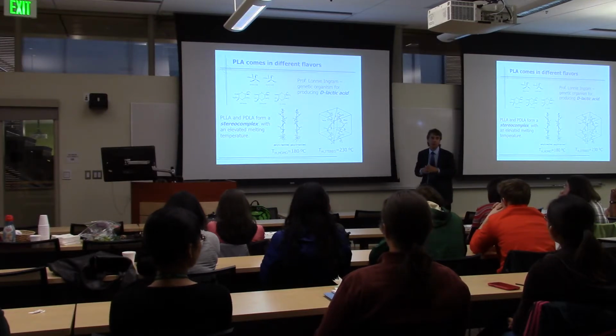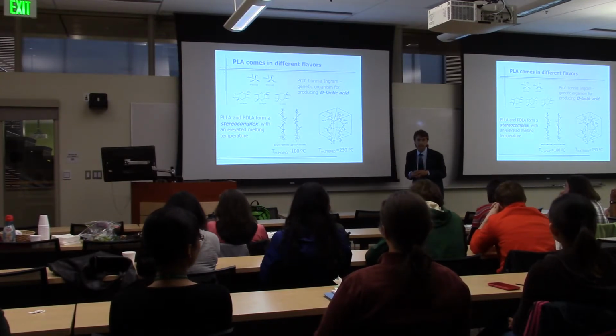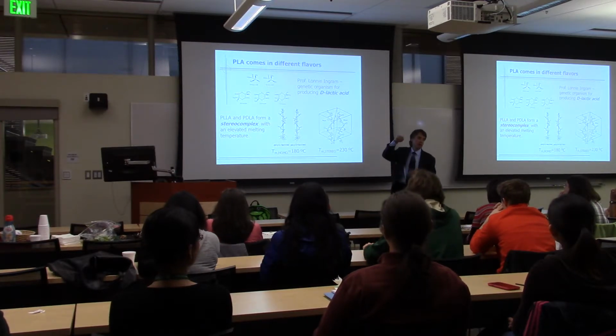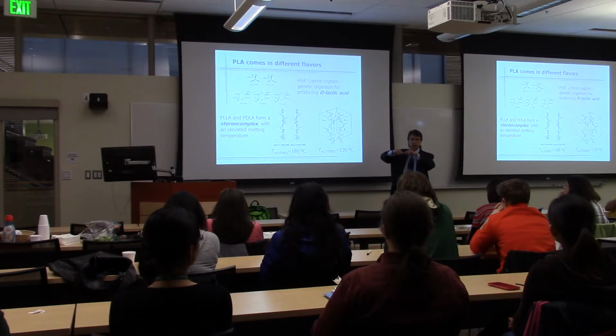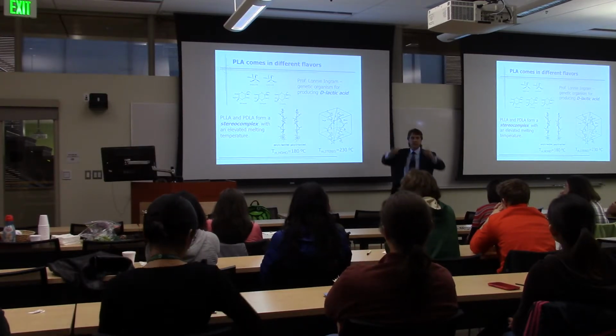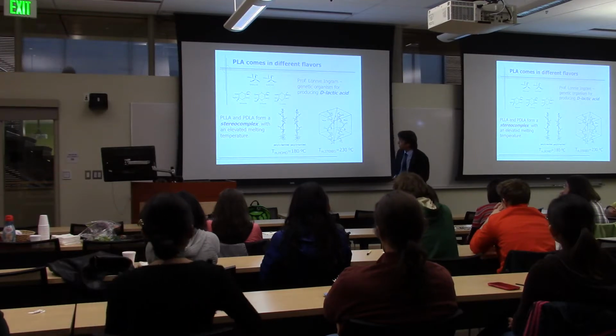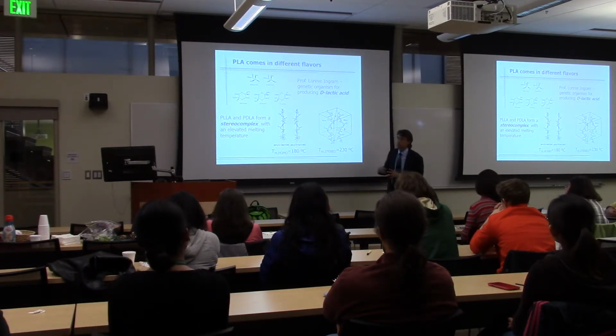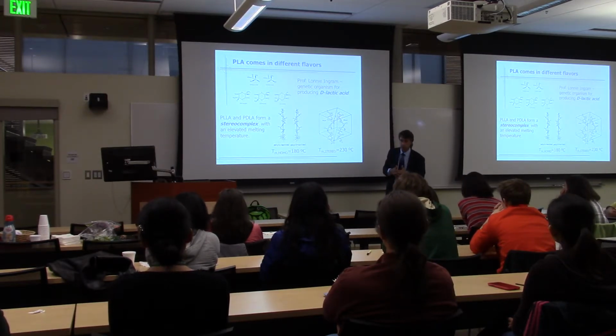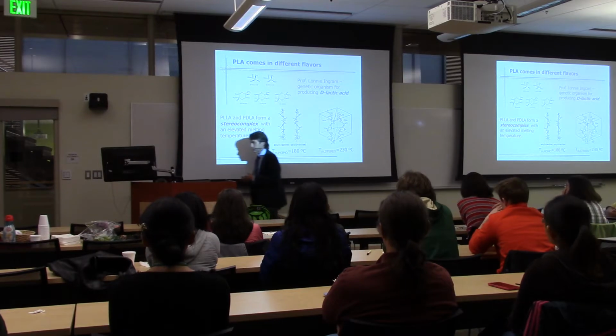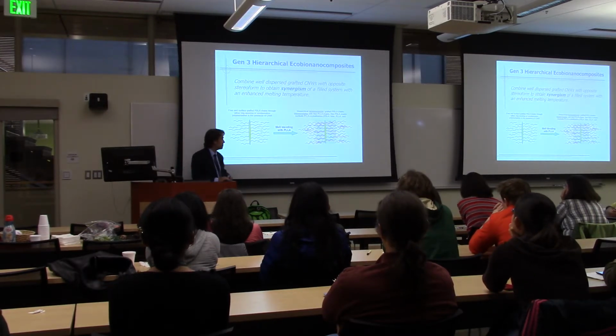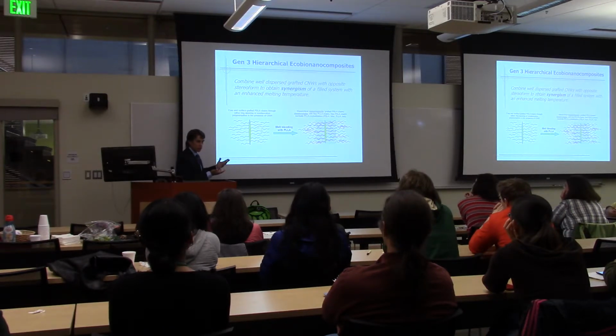And this happens even with the monomers. If you take LL and DD lactide, the melting point goes up. If you think of your usual eutectic, 2 crystals, there's a melting point depression; here it actually goes up in the middle, and at 50-50 it has the highest melting point. That's because you form a crystal structure where the helices can just pack together better. It gives you a more stable crystal structure. And of course, if it's more stable, it's harder to melt. Okay? And so your melting temperature goes up by 50 degrees centigrade. And so our idea then was why not combine our supramolecular structures with this other way to control material at this nanoscopic scale and incorporate this stereocomplexation.